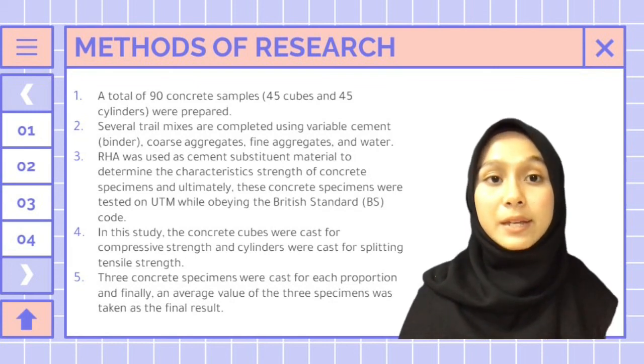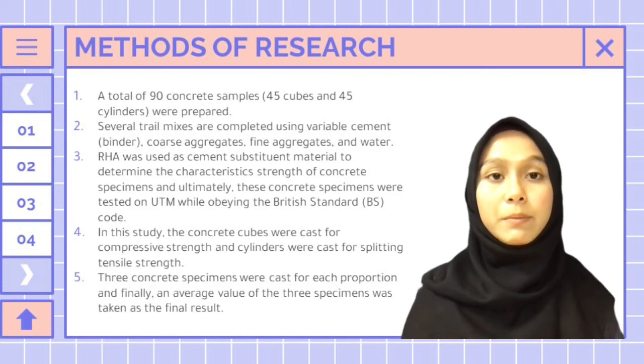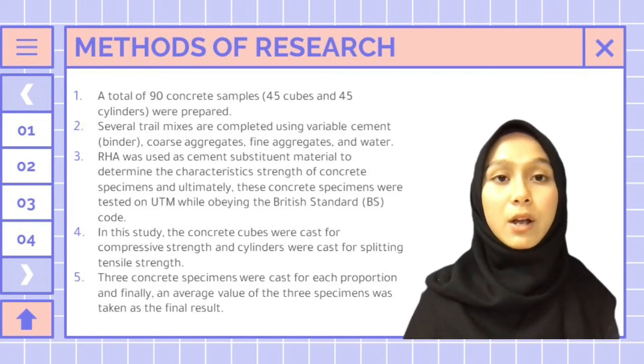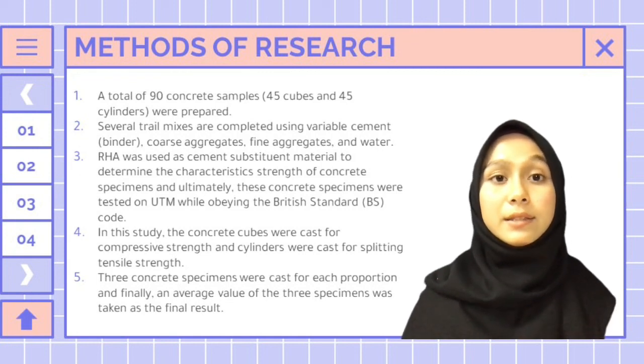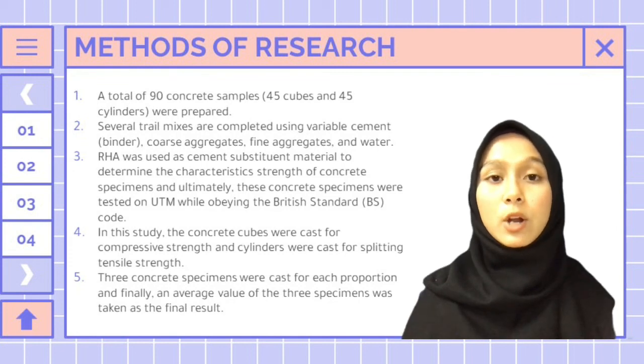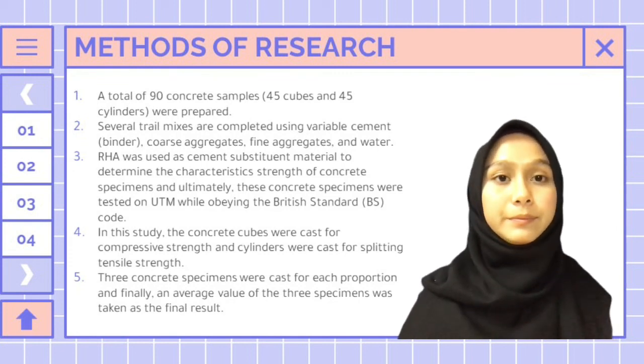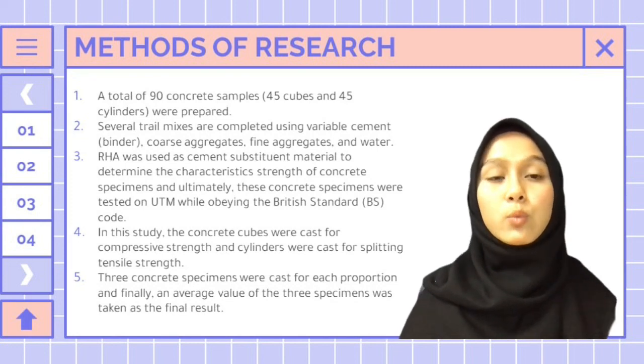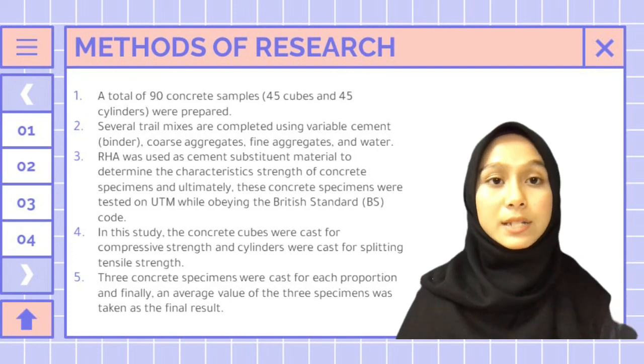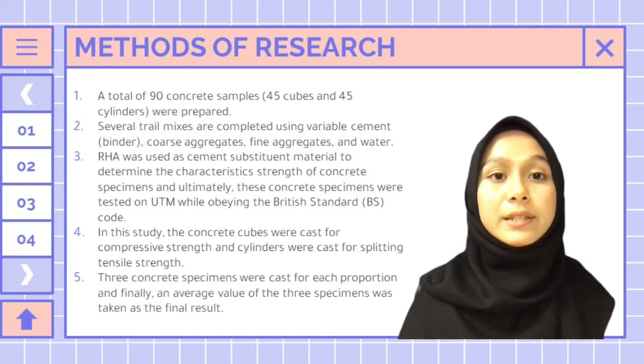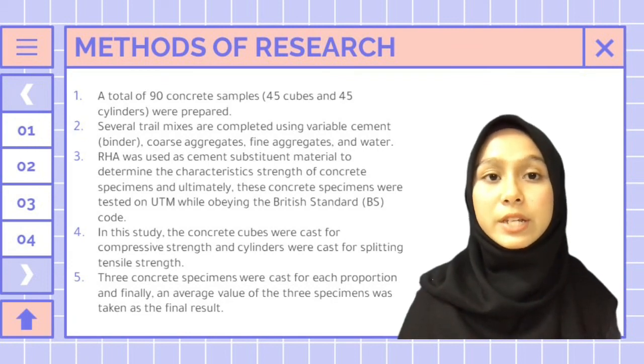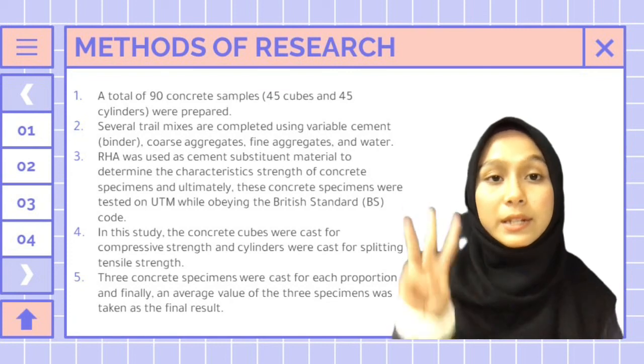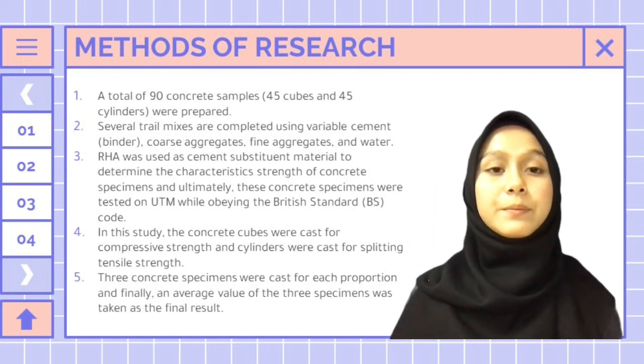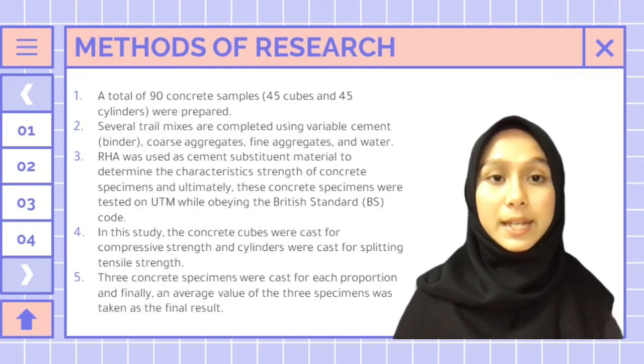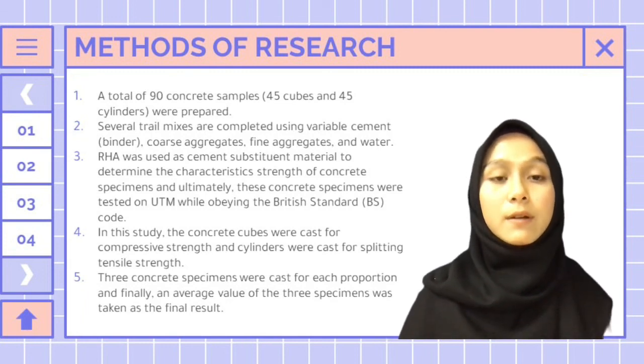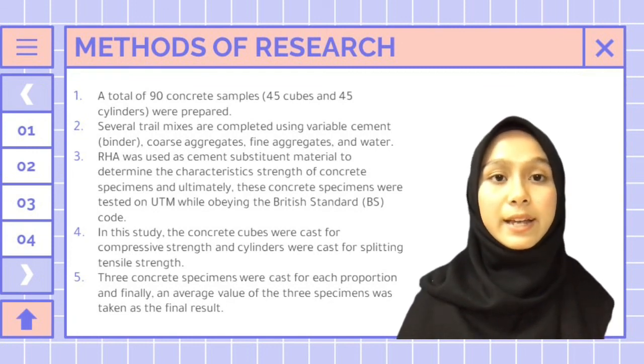While getting the desirable mix, RHA was used as cement substituent material to determine the characteristic strength of the concrete specimens, and ultimately, these concrete specimens were tested on a UTM while obeying the British Standard BS code. In this study, the concrete cubes were cast for compressive strength and the cylinders were cast for splitting tensile strength. Three concrete specimens were cast for each proportion, and finally an average value of the three specimens was taken as the final result. Based on this article, the work was completed in the concrete laboratory of the Department of Civil Engineering, College of Science and Technology.